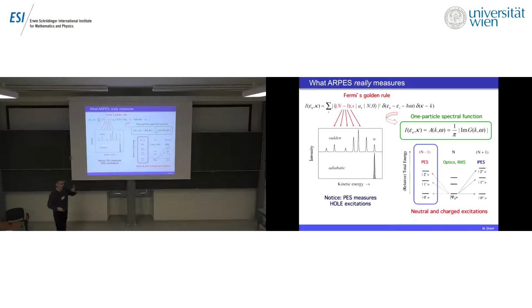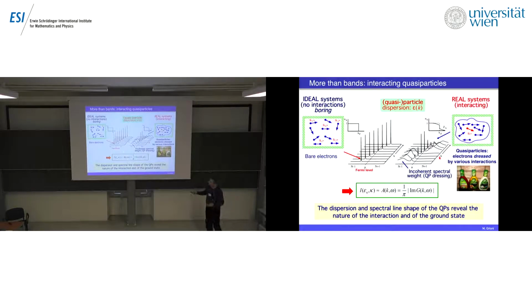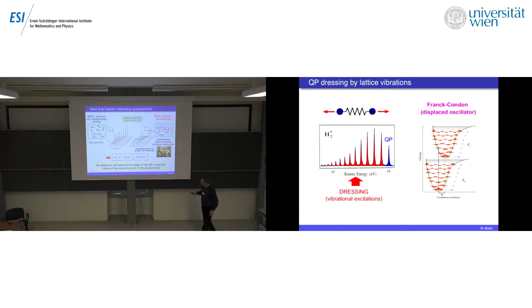So this is interesting. The comparison between theory and experiment works very well, because we have indeed something that corresponds very well to a fundamental theoretical quantity. Now, this is shown in a cartoon here. Here on the left, you would have a boring, non-interacting system. At each momentum, you have a delta function which disperses following a band. And in the interacting system, what you have here is the spectral function, which with all its complexities, instead of delta peaks, you have these quasi-particle peaks that are smaller, broadened, and then you have the dressing, which gives you these satellites.